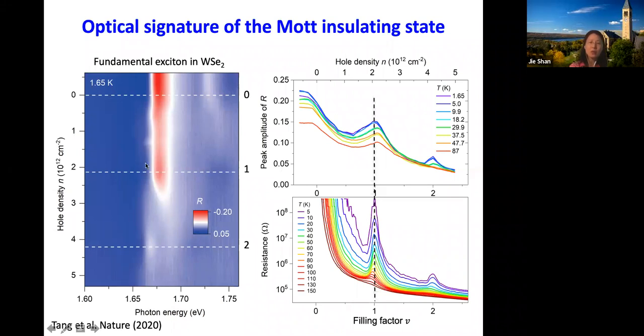So this is a contour plot of the fundamental exciton in WSe2 as a function of doping. This is nu equals 0, half filling, full filling. Unlike in a single monolayer, the exciton will quickly lose its oscillator strength as soon as you dope it. But here it keeps going a little bit longer. And you can also see some kind of modulations, right?